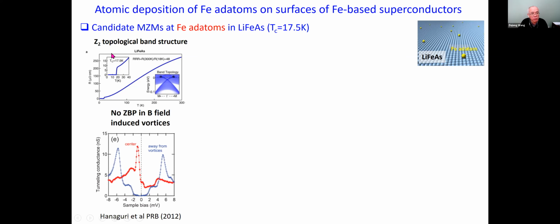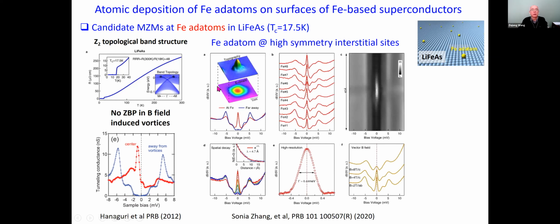Because the Z2 topological band structure is quite non-trivial, the vortices from the superconducting topological surface states are actually highly non-trivial here. Now, when they put the iron atom on top of LiFeAs, they see that the vortices actually get cleared up. And you see this zero energy peak at 8 of the 27 excess irons they looked at. They're at zero energy. And it may indicate that the exchange coupling can actually clear out these gapless states in the vortex in the presence of the magnetic ion.